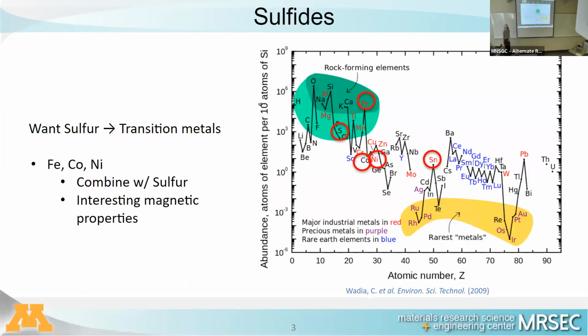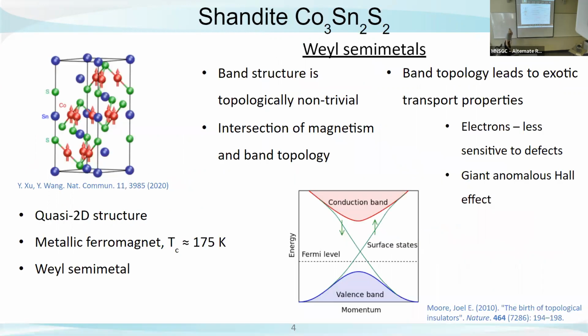Well, it turns out that we really want to see the magnetic properties that we can use for electronics. So adding sulfur with transition metals like iron, cobalt, and nickel can show kind of these interesting magnetic properties. And if you look on this image of abundance versus atomic number, you can see that all of these elements are pretty abundant and not going to go away super fast. So using them is another great quality of that sustainability aspect. And one of the sulfides that we are interested in is this shandite. It has a quasi 2D structure.